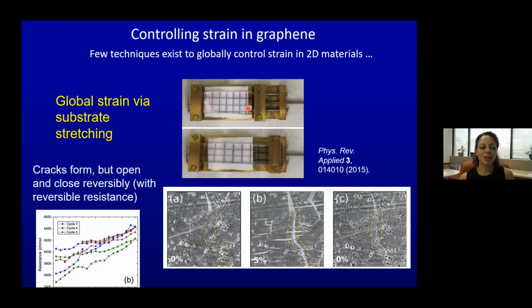And okay, so what did we see? What we saw is kind of what you might expect, which is that the graphene actually just ripped. Okay, because we were just applying this global strain. So we saw that first the graphene was unripped, and then as we applied strain, we got a crack that was a little bit bigger. And if you apply more strain, the crack gets bigger. But the interesting thing we found is that when we decreased the strain again, the crack completely disappeared, or almost completely disappeared. So this was something that we found unusual, because usually if you take a pencil and you break it in half, and then you try to put it together again, the crack is still there. But in graphene, it almost disappears.